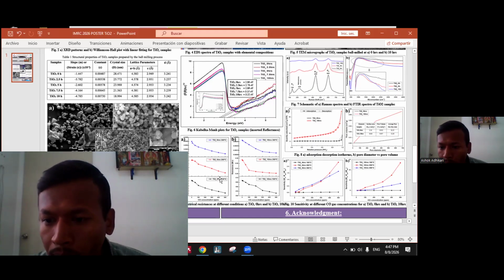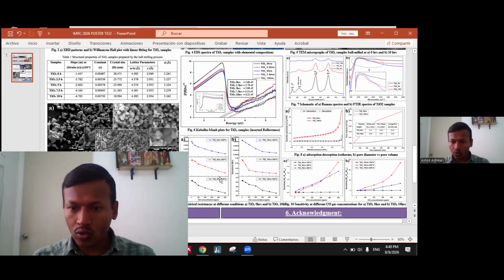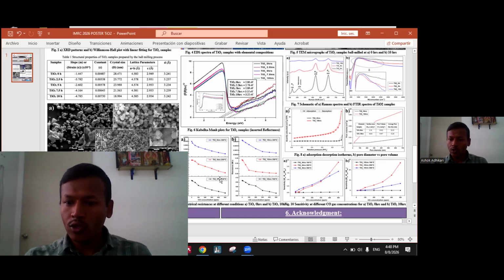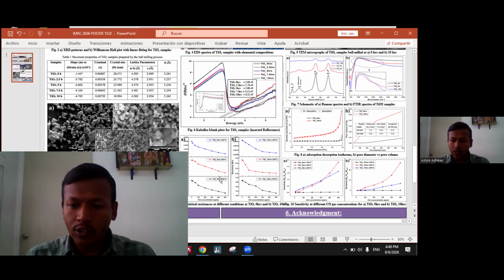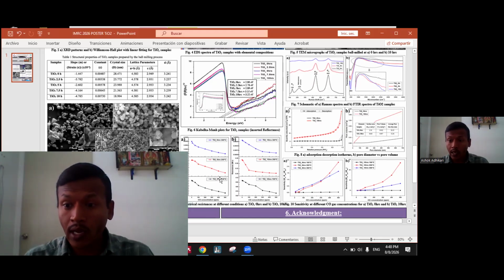And here we can see the samples. Our milled sample shows better results, and also temperature matters: a higher temperature shows better results. So in this case, for example, the sensitivity for the 0 hour sample, without milling, is around 2. And for the milled samples, it is around 30.